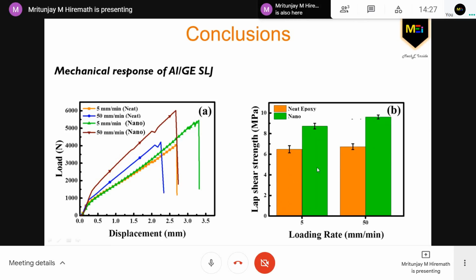on the right hand side, the shear strength is computed and plotted with respect to the loading rate. The test was conducted with respect to two loading rates, 5 mm per minute and then 50 mm per minute, for both adhesives. That is, this is for the neat epoxy, and this is for the nanofiller embedded epoxy.